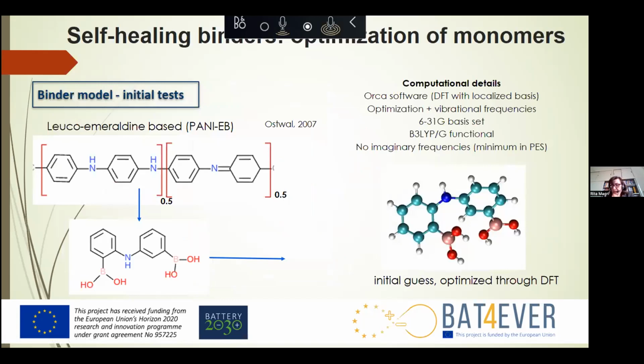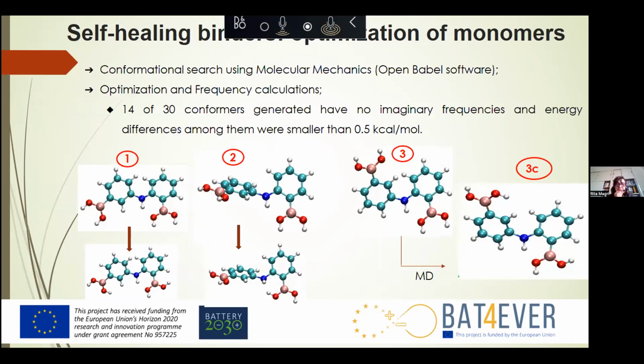Then we have also studied, and I go quite quickly on that, different conformers of these monomers. This was what we obtained from our partners, a suggestion for the boronic acid doped polyaniline. We have optimized this structure through DFT. And then we have studied different conformers, changing the disposition and orientation of the rings, the position of the nitrogen atom with respect to the boronic acid group, and so on. And then we have found 14. They have no imaginary frequencies, so they are stable and very close in energy.